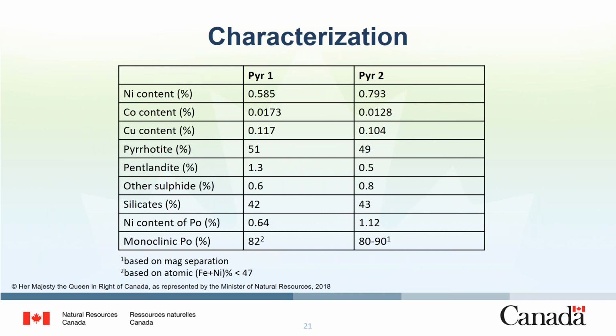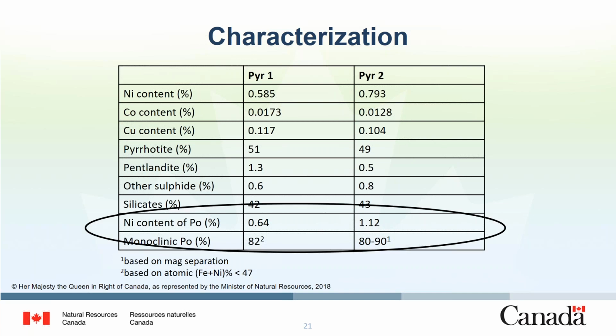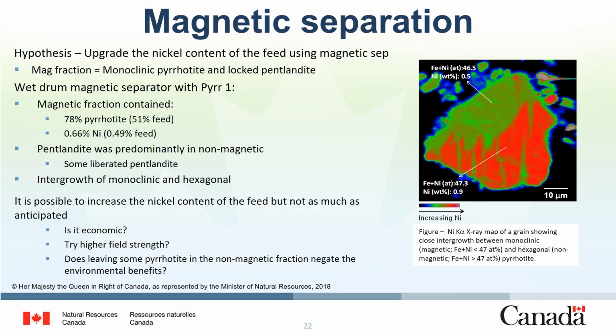2 characteristics led us to believe that we may be able to upgrade the nickel content of the material using mag separation. And those are, the first one, the nickel content of the pyrrhotite, which is higher than the bulk material in both cases, and the presence of primarily monoclinic pyrrhotite, which is strongly magnetic. We used a wet drum magnetic separator with 1 sample. Our basic hypothesis was that monoclinic pyrrhotite and the locked pentlandite would report to the mag fraction. As a result, the nickel content of the mag fraction would be significantly higher than that of the non-mag.